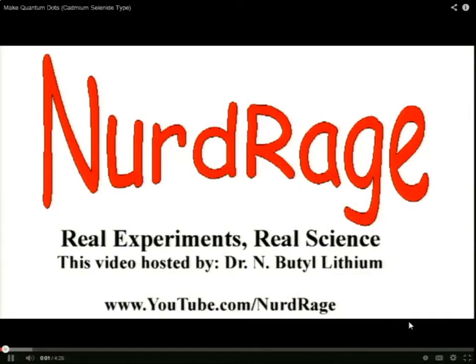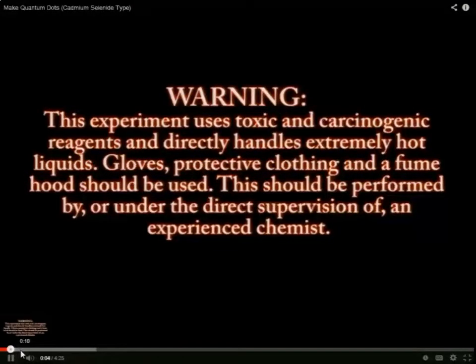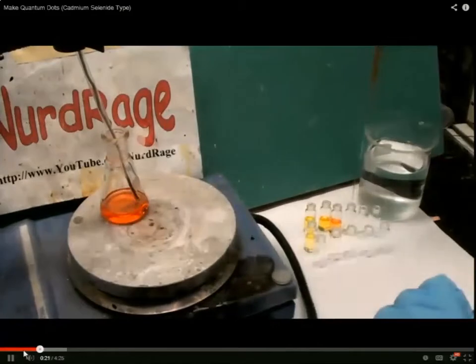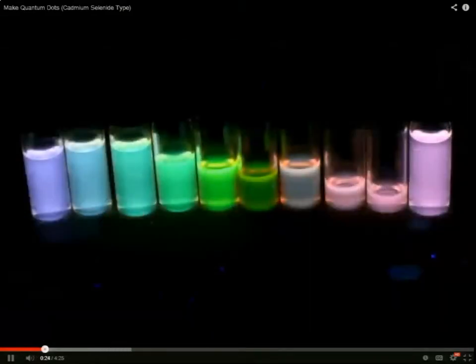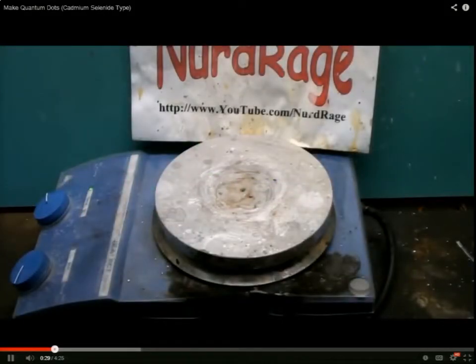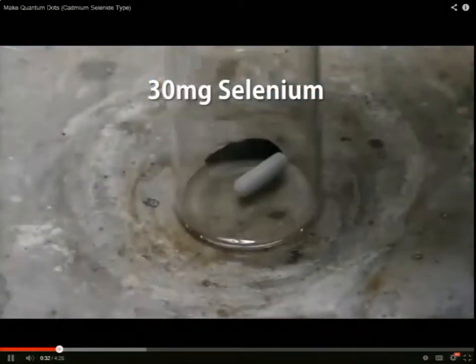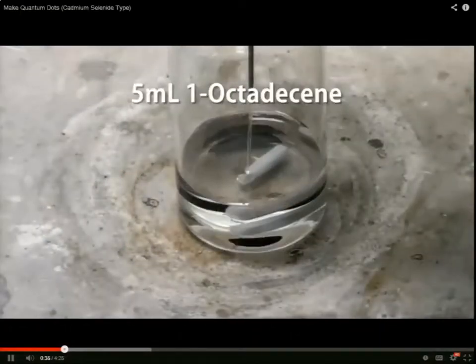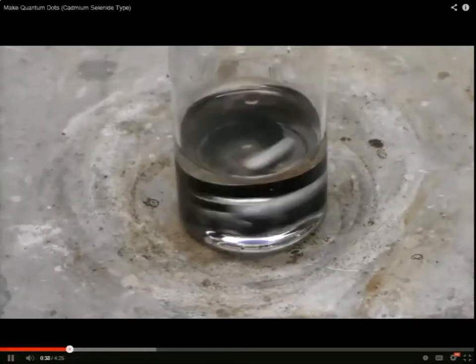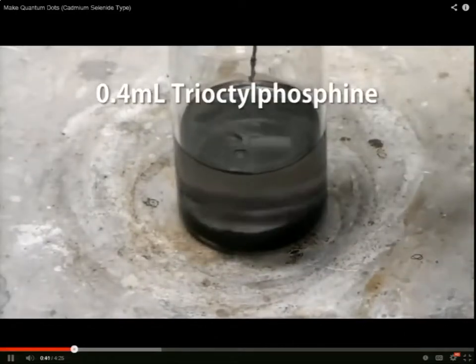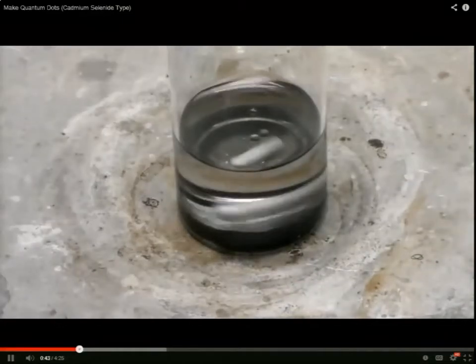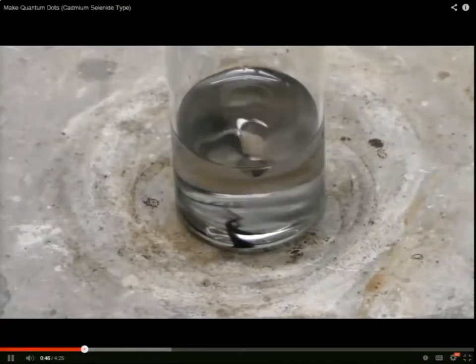It's an extremely simple tool, but also extremely pointy. Warning: this experiment uses toxic and carcinogenic reagents. In this video, we're going to make cadmium selenide quantum dots, a type of nanoparticle with interesting properties. First, we need to make our source of selenium. Get 30 milligrams of pure selenium powder and add to it a stir bar. Then add in 5 milliliters of 1-octadecene and turn on the stirring. Now add 0.4 milliliters of trioctylphosphine. Keep stirring and gently heat it until all the selenium dissolves into a clear liquid.